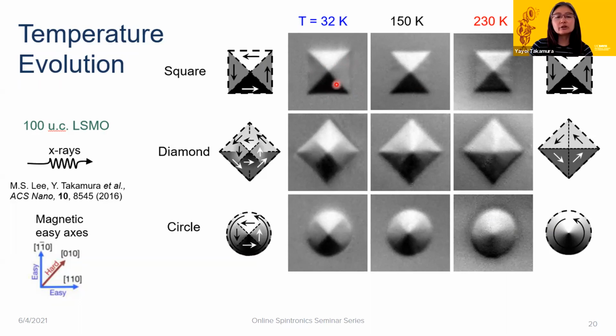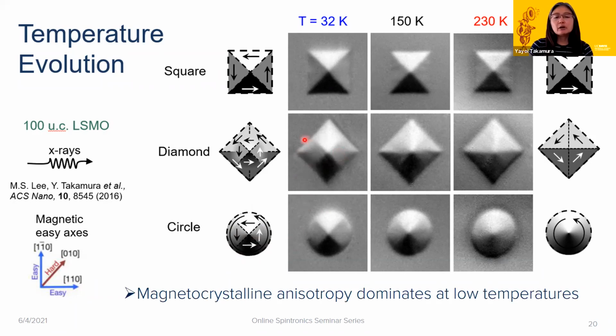just because the magnetization is getting stronger, but we get some interesting structures that appear in the center of the diamond and the circle structures. You can see that this center part, which didn't exist at higher temperatures, matches that of the square. So now what we have, as shown in these schematics, is a superposition of 2 different Landau structures, or a vortex and a Landau on top of each other. At the edges of the perimeter, shape anisotropy dictates what the edge of the nanostructure should look like, but magnetocrystalline anisotropy is dominating in the center. The magnetization wants to lie along the easy axes. So as we cool the temperature, we really see the dominance of the magnetocrystalline anisotropy at low temperature, and it goes away at high temperature.